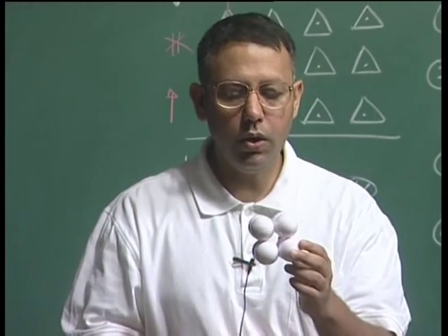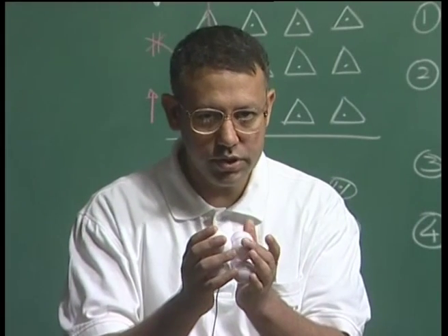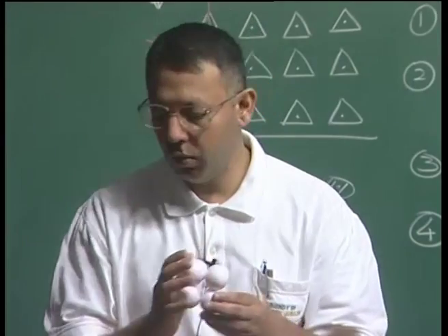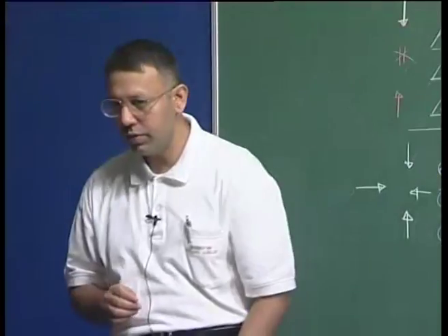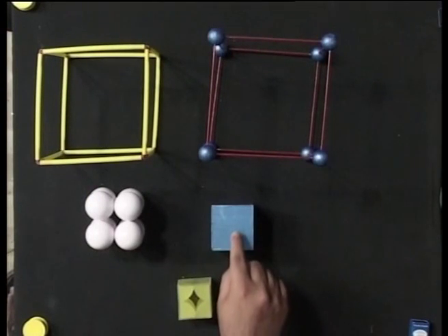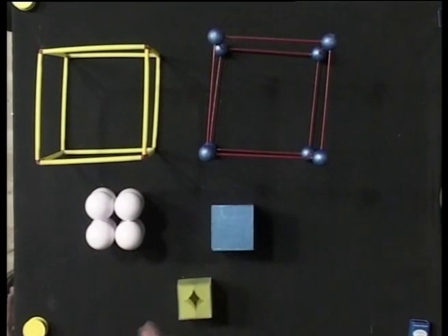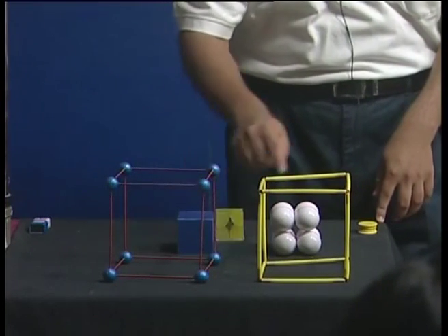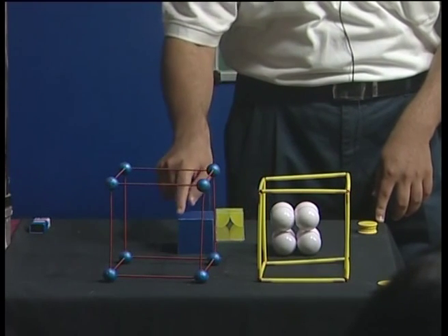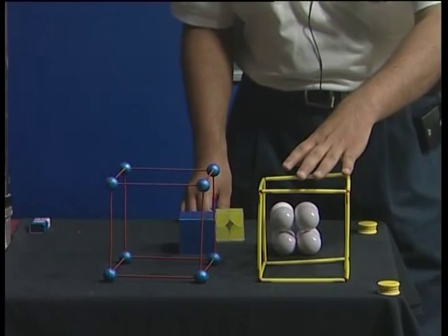Okay. And now if I were talking about an additional atom sitting there, then it is inside the void of this unit cell, and that is when we find it handy to talk about the void models. So that atom sitting in the center of this unit cell will be touching the 4 atoms at the top, the 4 atoms at the bottom, and therefore 8 atoms. So the polyhedron formed by the vertices of that coordination polyhedra is nothing but this void, which is a cubic void. Now you can clearly see this is space filling.